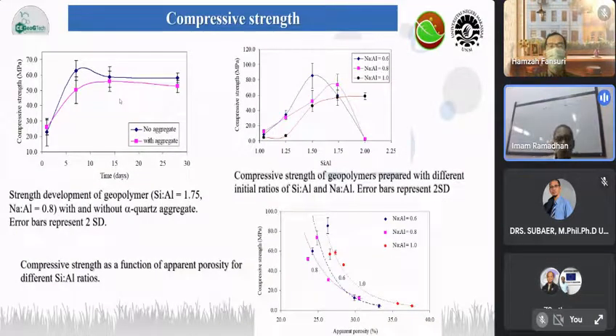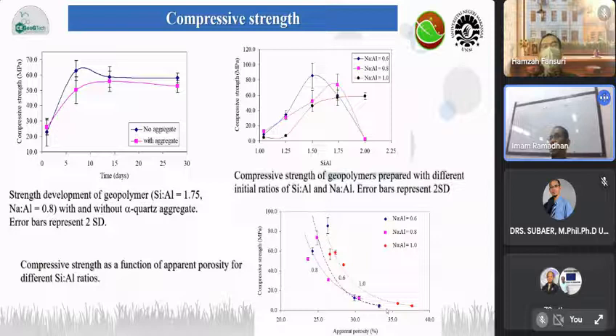I just want to show you that the influence of the aggregate in a lead scale is quite big actually in terms of the strength of the geopolymer. You can see here the influence of aggregate will reduce the strength of the materials a little bit, although the error bar is still acceptable. But the most influencing factor of compressive strength is the porosity, the apparent porosity.